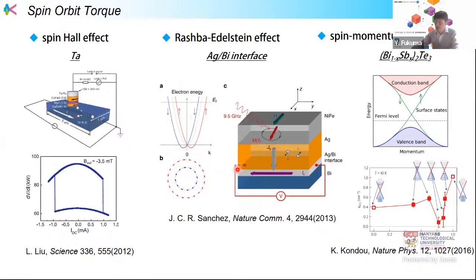Also, in the case of an interface, here is the silver bismuth interface. There is the Rashba effect. The Rashba effect shows this kind of spin polarized band structure, where the spin state depends on the momentum of the electron. For example, for an electron with this momentum, we can get that spin.